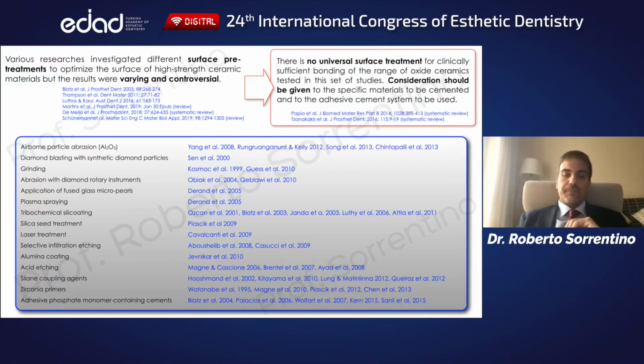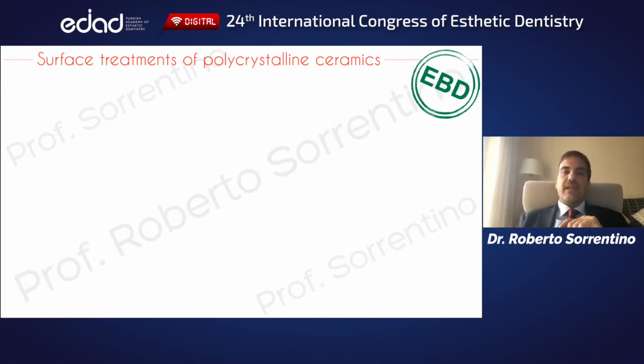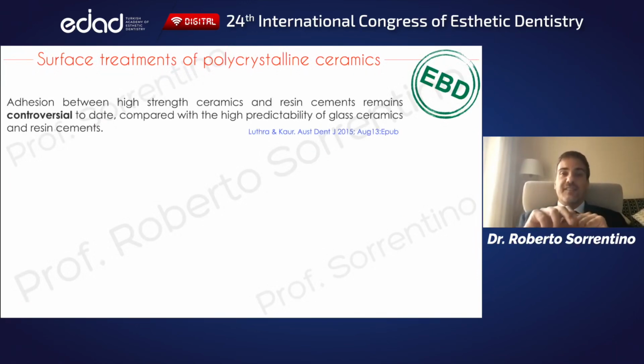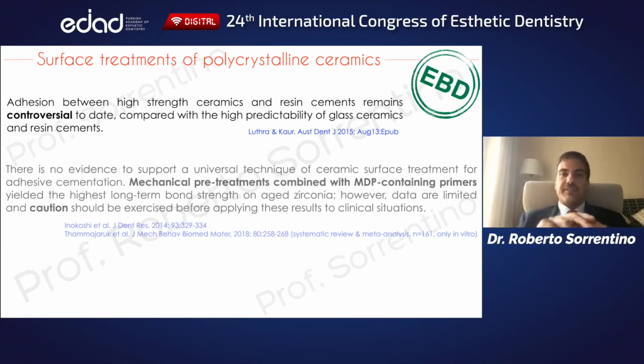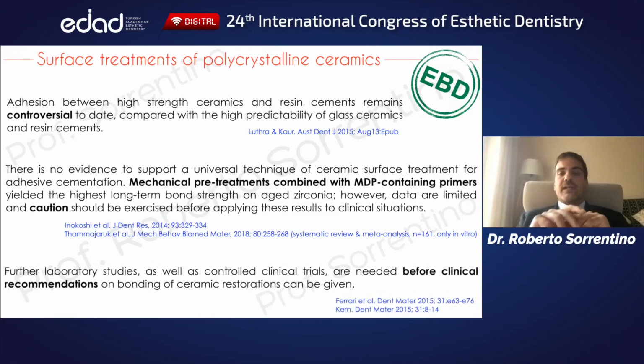There is no universal surface conditioning technique, and the indications still remain controversial, recommending careful evaluation of the cement to be used. To date, as regards pure polycrystalline cores, evidence-based data state that adhesion onto zirconia is still discussed and less reliable than onto glass ceramics. No consensus has been found yet about the ideal surface conditioning, but most authors agree about the combination of mechanical and chemical treatments, and that further laboratory and clinical studies are necessary to draw clinical recommendations about long-term adhesion onto zirconia.